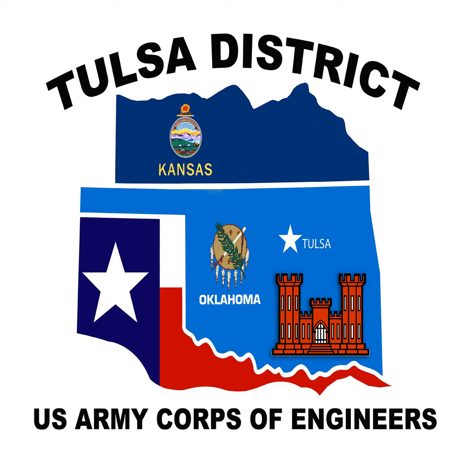And one of the most interesting projects we've done recently is actually related to the beams we were testing today, where we were looking at, could we repair one of these damaged ends with UHPC? And unfortunately for you guys, we finished those tests up a couple months ago, but we had damaged beams very similar to the damage you saw today. We encapsulated those ends with UHPC, and then we retested them, and we saw that we could actually increase the strength significantly by using UHPC as a repair material.